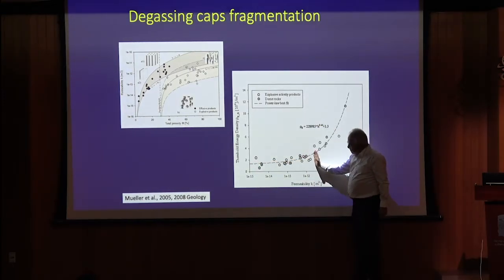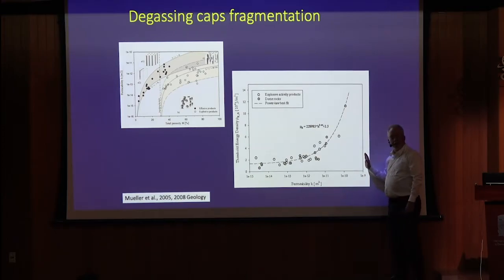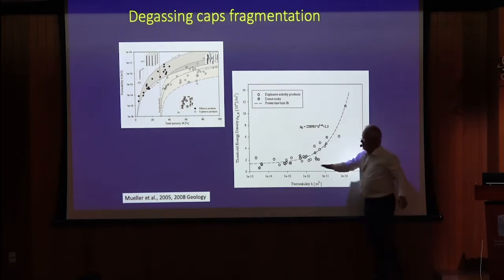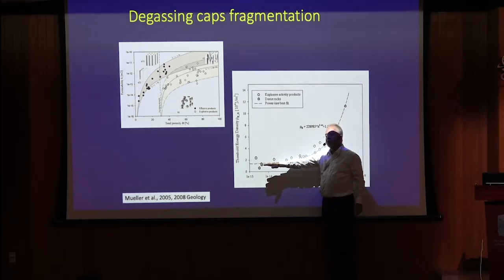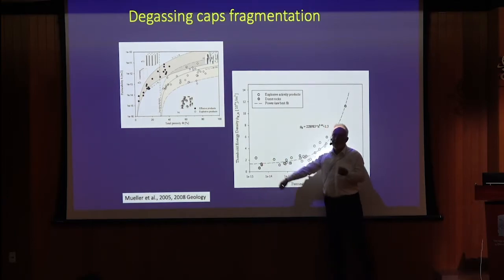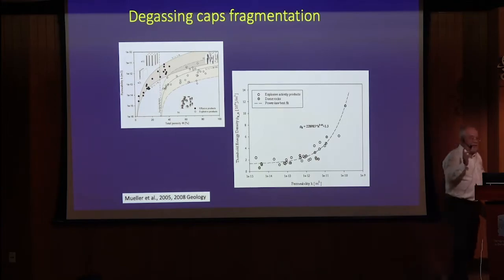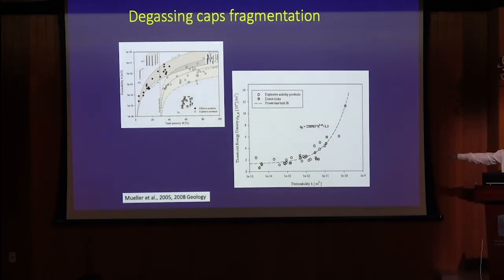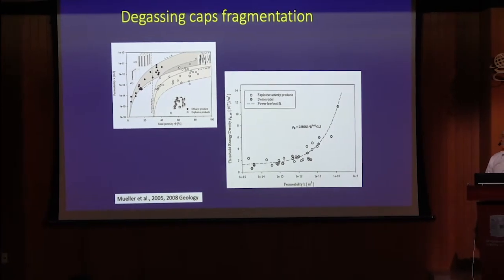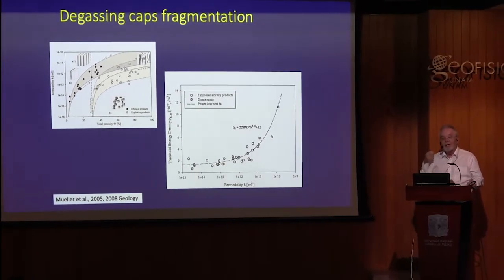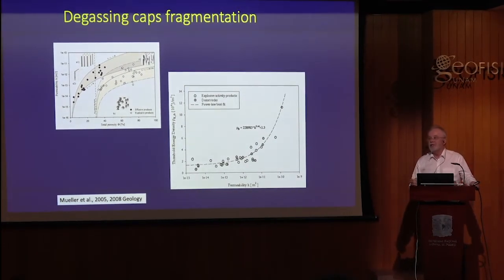for a range of permeabilities which are very, very low. But then if we start working with rocks which have permeabilities which are high, it starts to run away. It's no longer a constant. Our assumption of a constant fails. So we're out of the regime where we can talk about a simple threshold of energy to break these rocks. And there was a whole PhD thesis which was involved in measuring the permeability of every single sample that we used in these experiments.